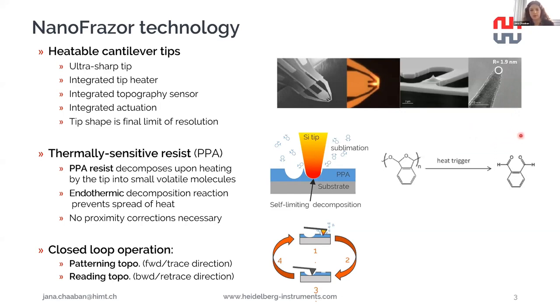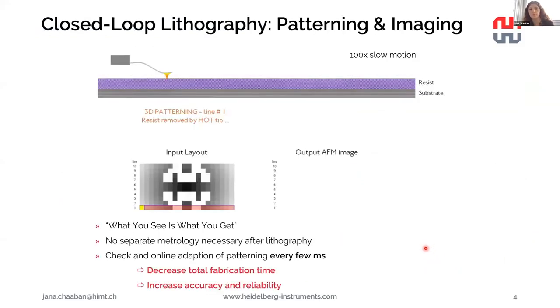What's also very important for the NanoFrazor principle is that we combine the writing with the reading, and this is done all in situ using the same cantilever tips illustrated here. In addition to an integrated microheater, which you see glowing in this picture, we also have an integrated topography sensor on the same cantilever tip, which is used to image the patterned samples. We also have an integrated actuation that can very accurately move this cantilever tip up and down. We combine these reading and writing capabilities to perform so-called closed-loop lithography patterning. You can see it illustrated in this video here.